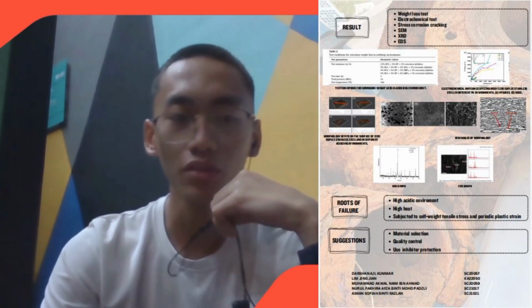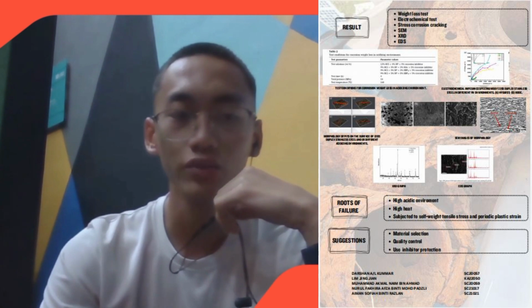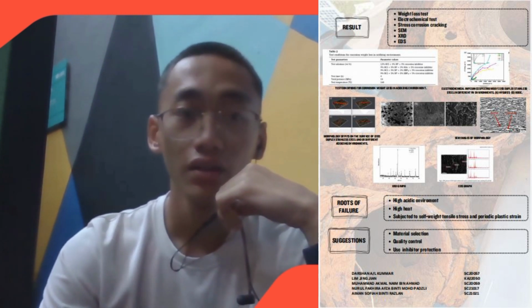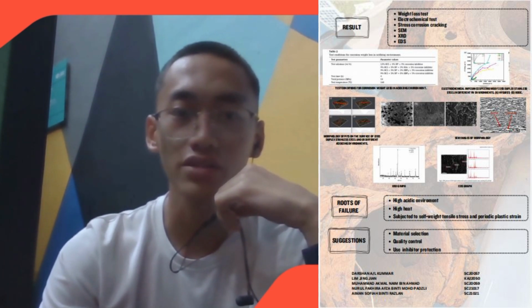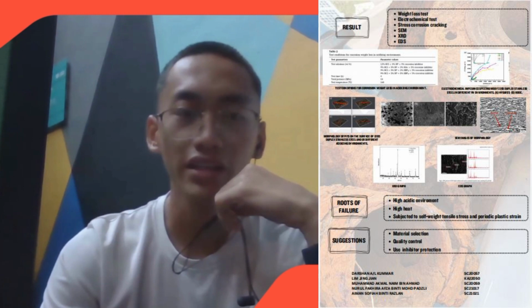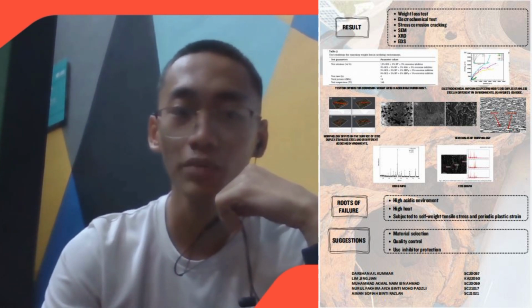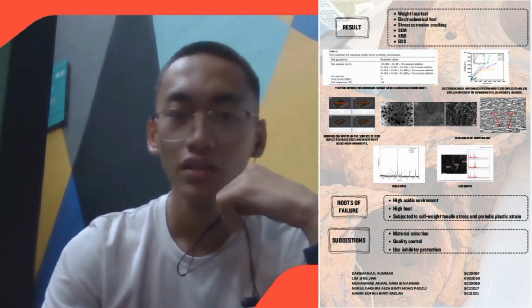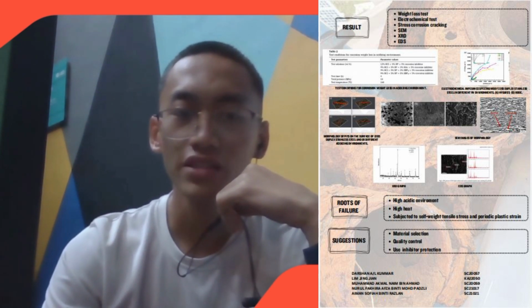Today, I would like to talk about the root cause of failure in 2205 duplex stainless steel coil tubing. The increasing demand for oil and gas resources has led to the development of high pressure and high temperature wells. These wells are characterized by harsh working conditions such as elevated temperatures, high pressure, highly mineralized formation water, and the presence of corrosive gases like carbon dioxide and hydrogen sulfide. The combination of these factors creates an aggressive environment that accelerates the corrosion process.